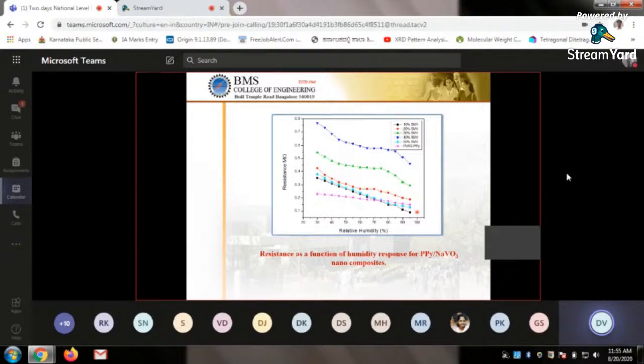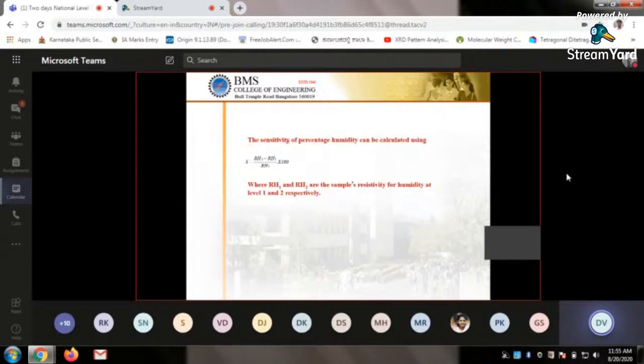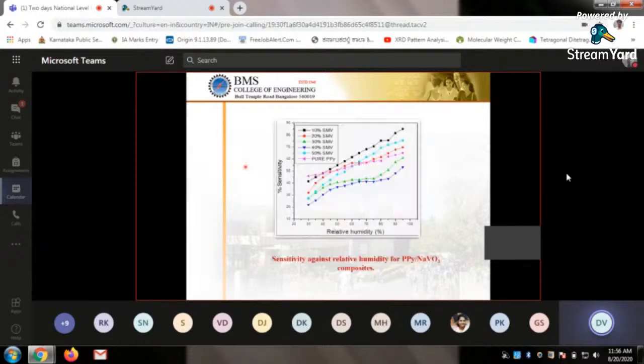It should be a linear variation. So one more thing we can plot. What we observed was, again, 40% gives you better values, and it is almost linear also. We have not plotted the linear regression, and we have not studied further. Anyway, we can calculate the sensitivity percentage of humidity. How? S can be calculated with this equation: RH2 minus RH1 divided by RH1 into 100. RH1 and RH2 are the sample responses for humidity at level 1 and level 2. What is level 1 and level 2? Level 1 may be room temperature, or it may be at 20 RH. Level 2 may be a different RH. So you can calculate sensitivity. It's called percentage sensitivity.